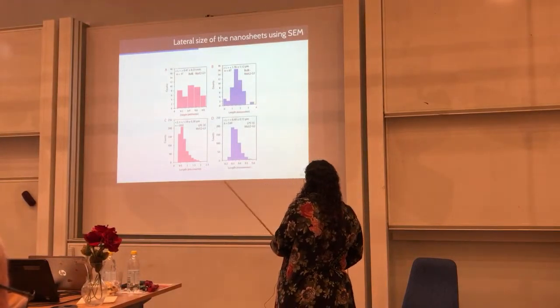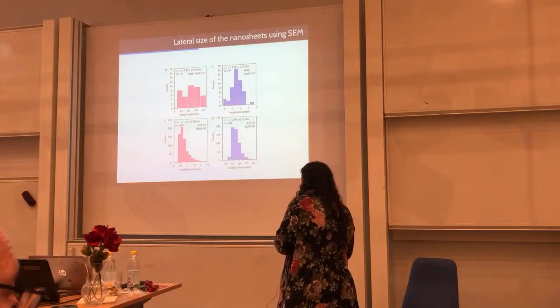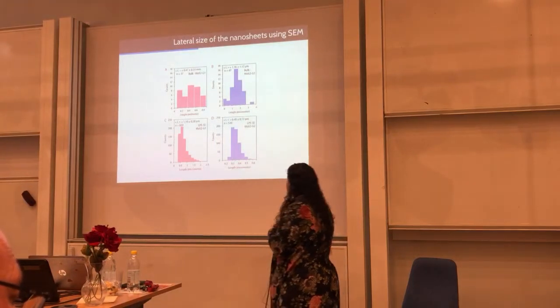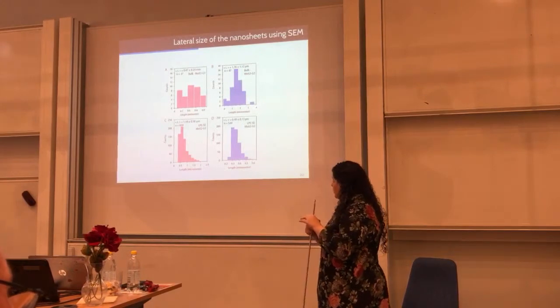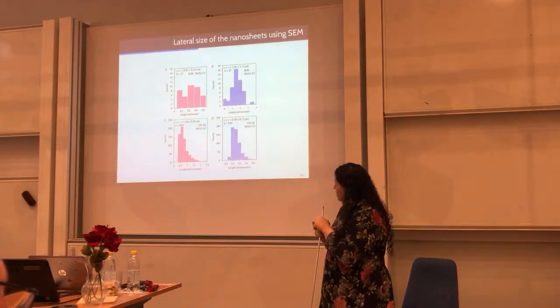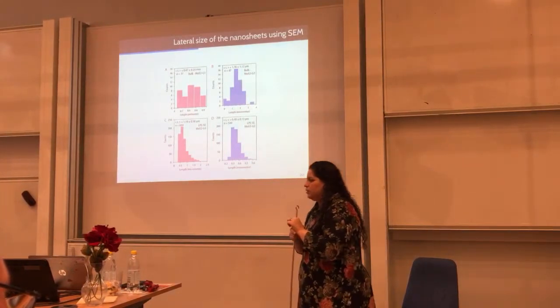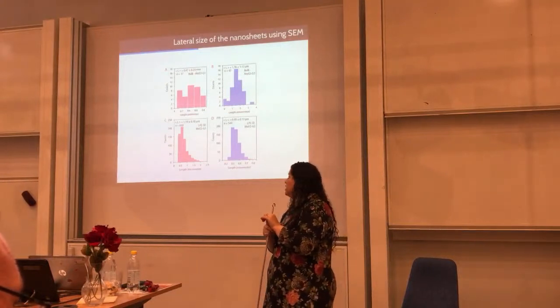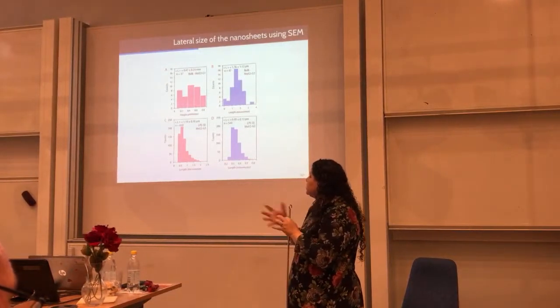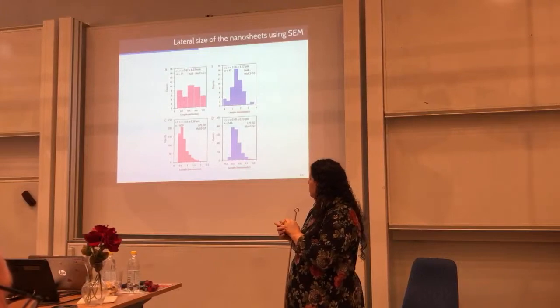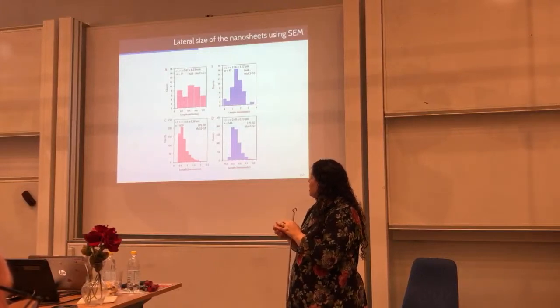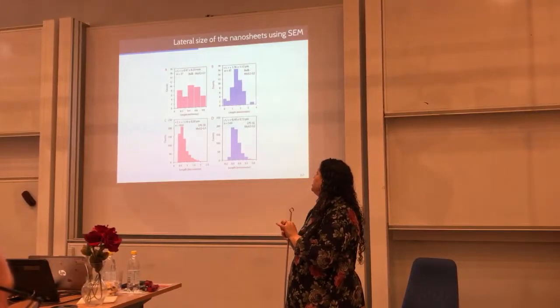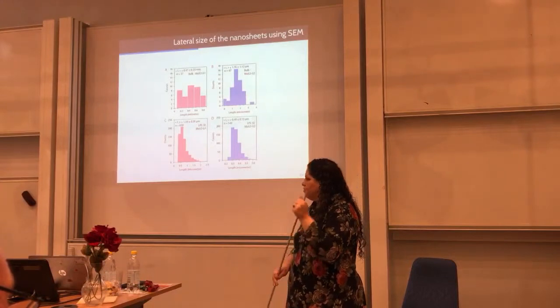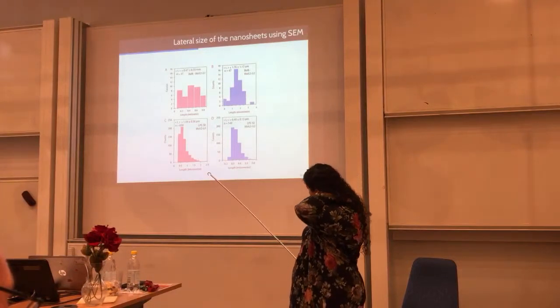Okay, so there is another technique that we are using here at the university in our group to measure the size of the particles: we deposit a drop of this layered material dispersion on a polished aluminum stud, and then we measure the size. We could also deposit it on a silicon wafer.